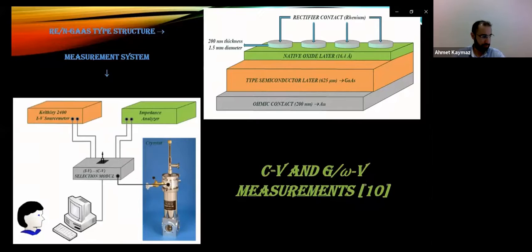Of course, the following question may come to mind. Why was the measurement performed at 1 MHz frequency? The reason can be explained as follows. The charges at surface states or traps can easily follow the AC signal at low frequencies, that is, at frequencies below 500 kHz. These charges or traps can yield an excess capacitance and conductance which depends on frequency and lifetime.